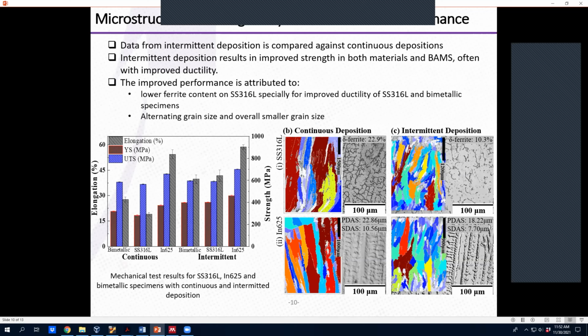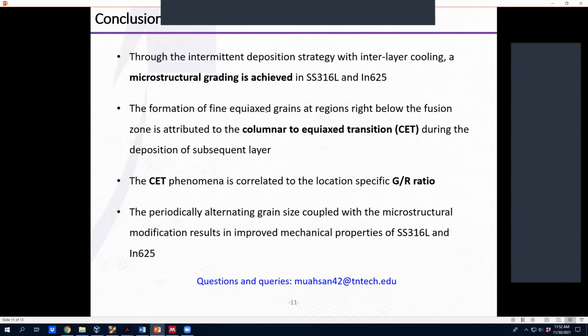So based on these results, we conclude that through the intermittent deposition strategy, we can achieve microstructural grading in wire additive manufacturing. This microstructural grading is achieved through a columnar to equiaxed transition during the deposition process, and this transition is a result of the local G by R ratio. Also with this approach, we can have improved mechanical performance in the WAM structures.